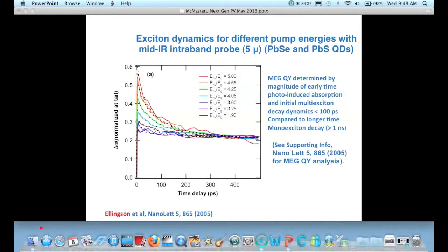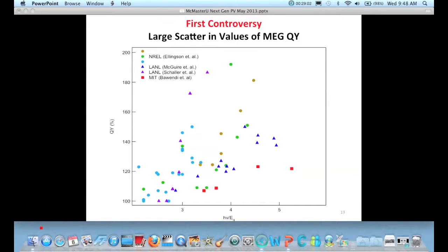So that just shows data that was reported. It was first reported by the Los Alamos group led by Victor Klimov, and they sort of found it accidentally. We were looking in the III-Vs for this, but didn't see it. It's harder to see. It's very easy to see in the IV-VIs, like the lead compounds: lead sulfide, selenide, telluride. But the data was scattered all over the place. This led to a controversy, in that people either could not reproduce these results, or when they did, they said it was a small effect.